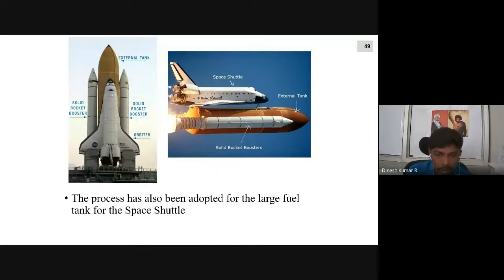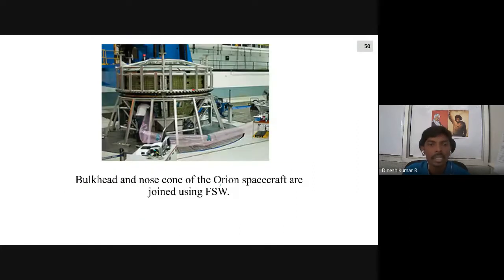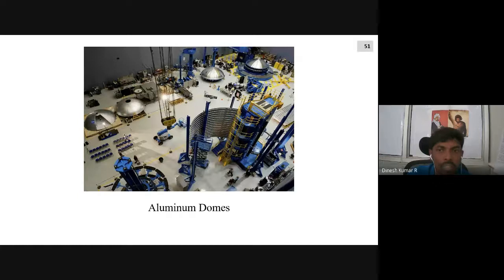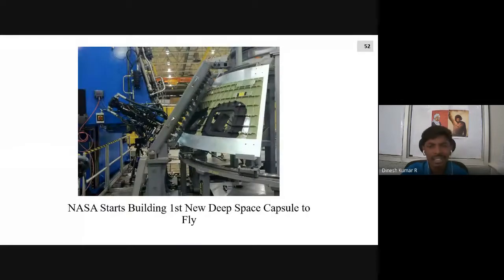This process was later adapted for space shuttles. Then the bulkhead nose, which is at the edge of the rocket launches, was also made with this process. The dome at the top, this particular portion, was even welded by the FSW process. Earlier it was done by other welding processes with not much efficiency, so they were increasing the thickness, but now with limited thickness they were able to achieve better strength, so they have adopted this technology for joining these components. And thirdly, even the space capsule was utilizing this FSW process.